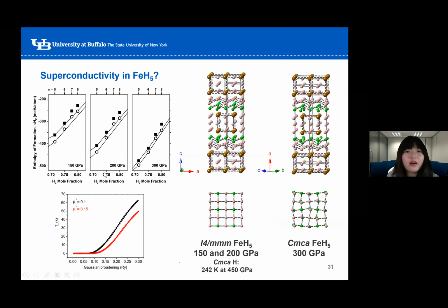So here it shows the convex hull at three different pressures. At all the pressures, FeH5 is located on the hull, and FeH6 is on the hull at 300 GPa and within 9 meV per atom above the hull at lower pressures. For FeH7 and 8, the structures are within 10 meV above the hull at 300 GPa, but further away from the hull at lower pressures. So although several phases are not on the hull, we believe the distance to the hull is relatively small, and because they are dynamically stable, we analyze all of these structures.